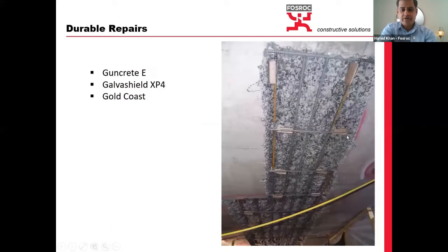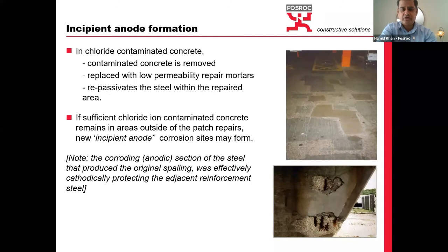So for durable repairs, getting it right the first time and avoiding any side effects, it's always better to add an anode at the perimeter, because I'm not sure if you've heard of the concept of the incipient anode effect. I'm sure you must have. That means if you have repaired a certain area and removed the deteriorated concrete, then after 6 months or 1 year, the adjacent area starts getting corroded. This is a side effect, by the way. It is called the incipient anode effect, or the halo effect, or ring anode effect.